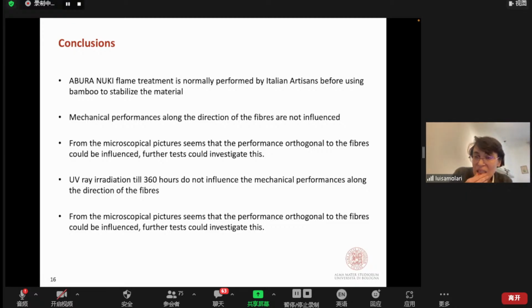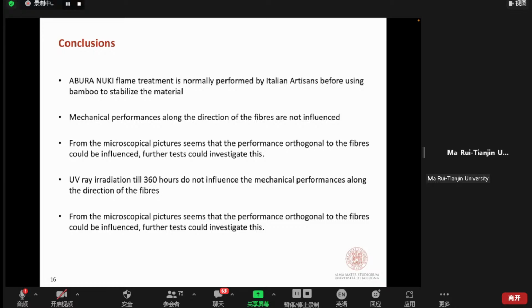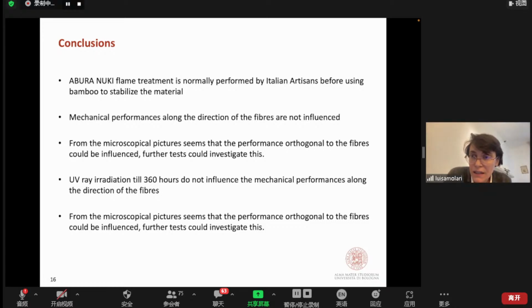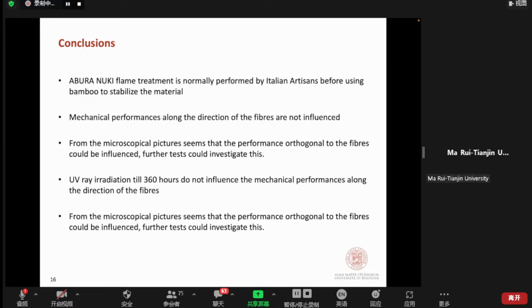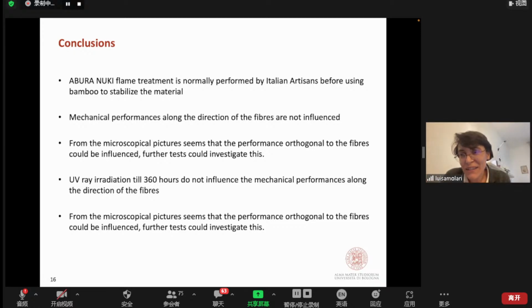So the treatment makes no disadvantages, and again the mechanical performance in the circumferential direction, orthogonal to the fiber, should be investigated more. Okay, I'm finished. Just one last thing. We also need to go further with the duration of the irradiation, because we started to see slight damage on the mechanical performance.